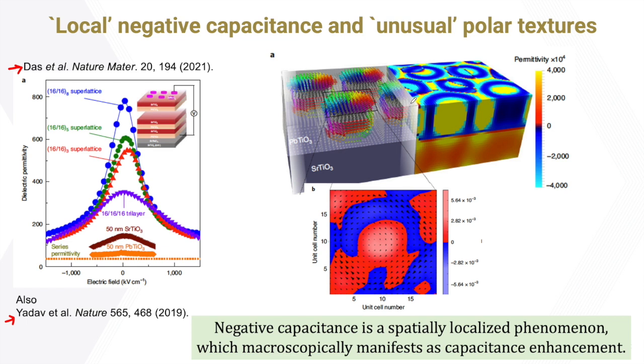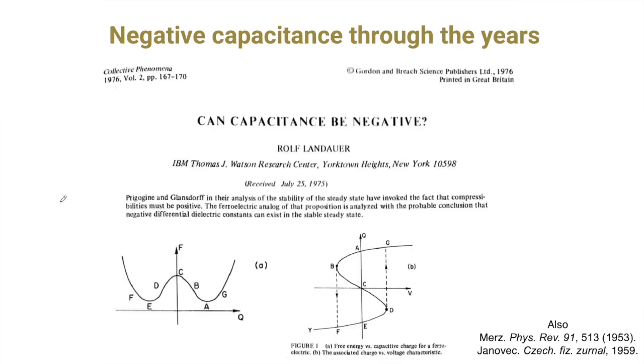In other words, in the ferroelectric material, there can be different regions of negative local permittivity and positive local permittivity. So this essentially says that the microscopic picture deviates significantly from the macroscopic picture that we started working on for negative capacitance. In other words, negative capacitance is a spatially localized phenomenon within the ferroelectric layer, which macroscopically manifests as capacitance enhancement. Although we are talking about negative capacitance only recently, over the last decade or so, negative capacitance was mentioned multiple times in literature even before that.